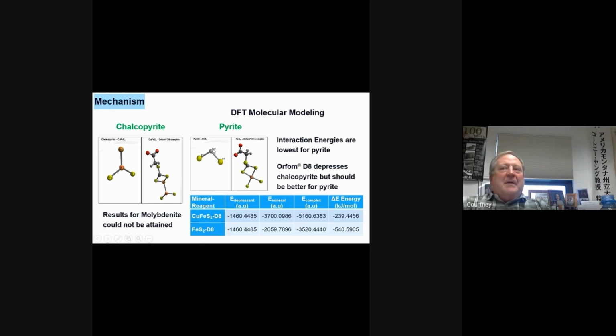In moly, no matter what you do, the molybdenum is below the surface. The surface is always sulfur. So you don't have to do anything, and it's naturally hydrophobic. You can make it more hydrophobic with diesel fuel and other organics like that, but diesel fuel obviously works the best, and it loves to adsorb onto the moly. So we learned a lot from this DFT modeling. We presumed that it was a monodentate here and here, and we just tried to get that to work with the molybdenite, and we couldn't get that bond to theoretically form by the computer. It just wouldn't. And so we associate that with the molybdenite being naturally hydrophobic.